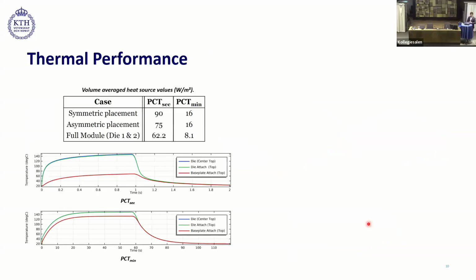So first, we will look at the thermal performance of the solder layers. The thermal performance was done using power cycling tests, PCT-sec and PCT-min. According to the ECPE AQG 324 standard, they divide the power cycling into 2 different categories: PCT-sec, meaning the heating time is less than 5 seconds, and PCT-min, meaning the heating time is more than 15 seconds. So PCT-sec can also be said as a fast power cycling test, and PCT-min can also be termed as a slow power cycling test.